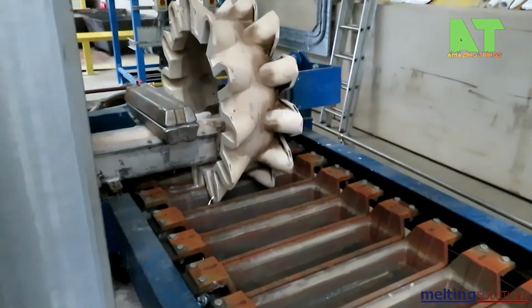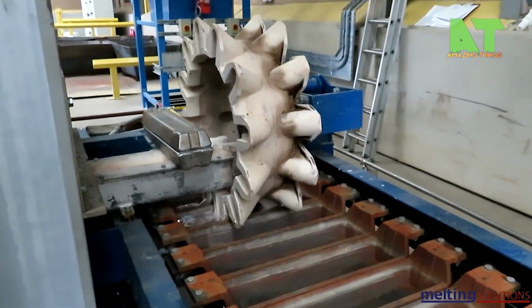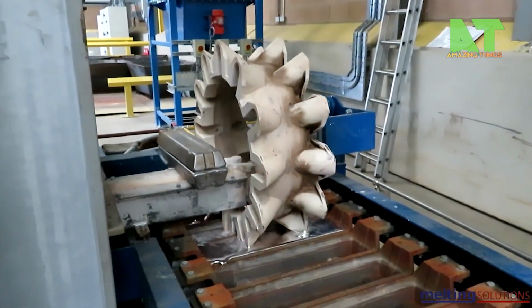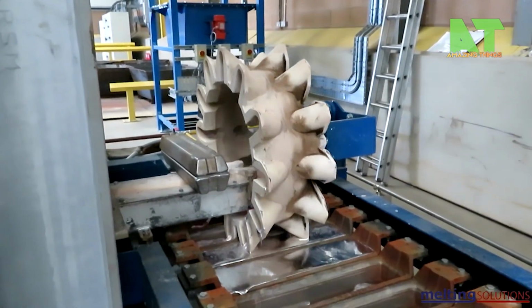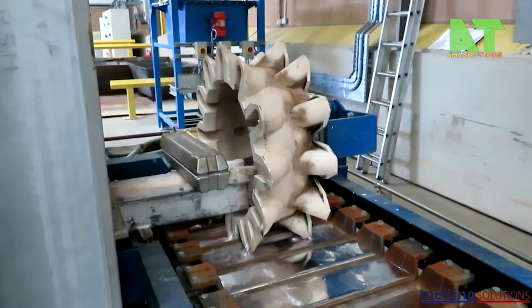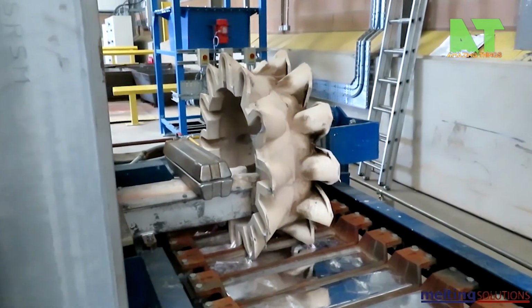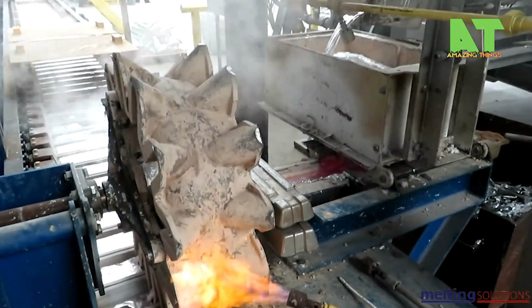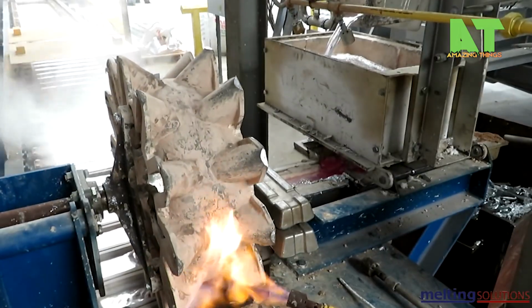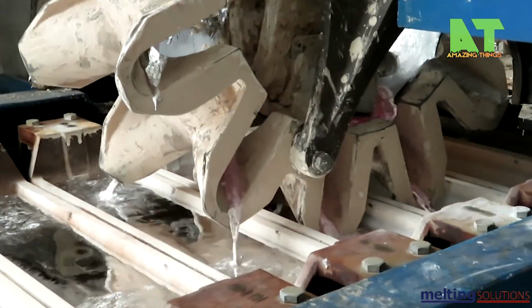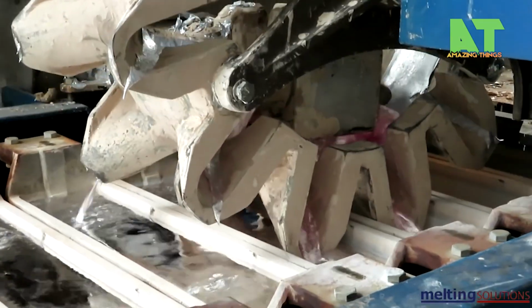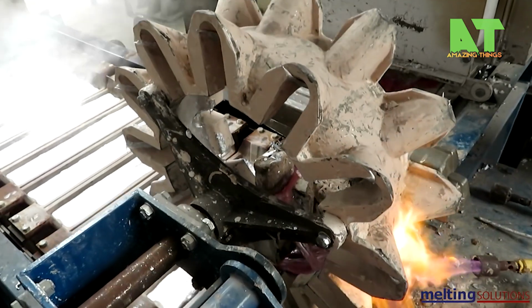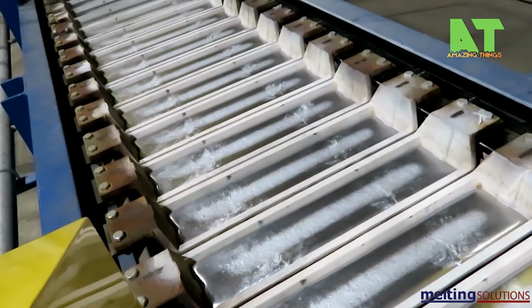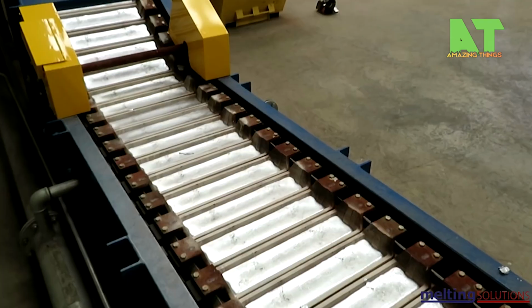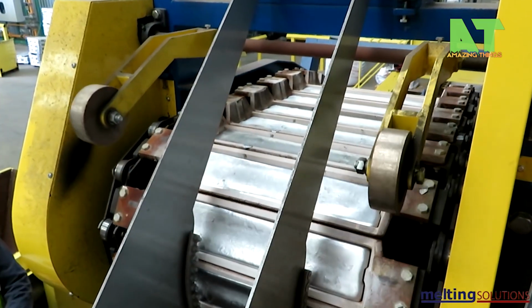From there, the molten metal is transferred to the 15-ton tilting shaft holding furnace, a specialized unit designed to maintain the liquid metal at a stable temperature while preparing it for casting. What makes this furnace truly impressive is its porous plug gas injection system. Inert gas, typically argon or nitrogen, is forced up through a porous ceramic plug at the furnace floor, bubbling gently through the molten bath. This process, called degassing, removes dissolved hydrogen and other impurities that could weaken the final product. The result is cleaner, denser, higher quality metal ready for casting.